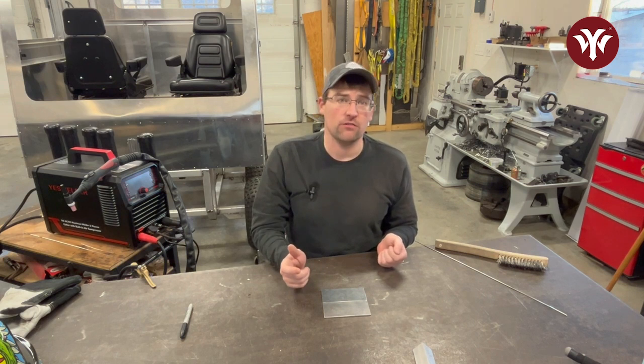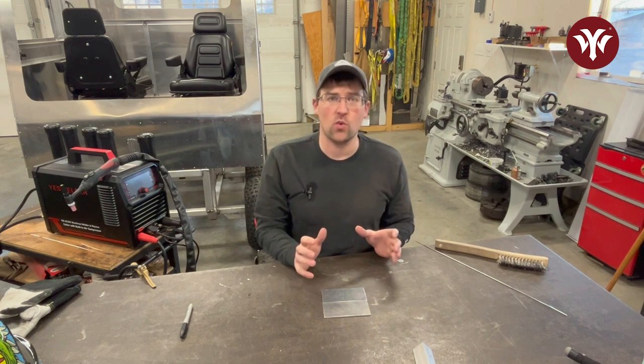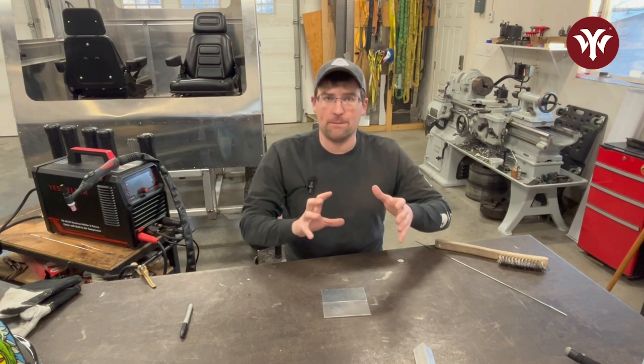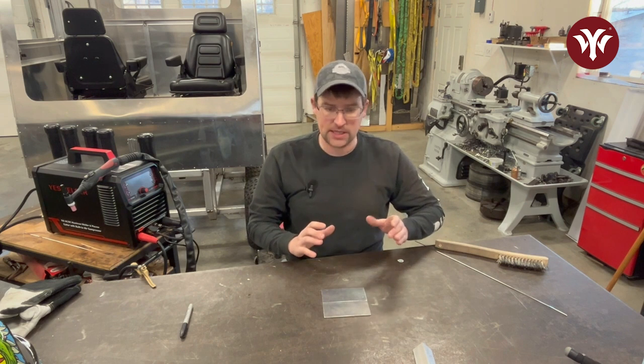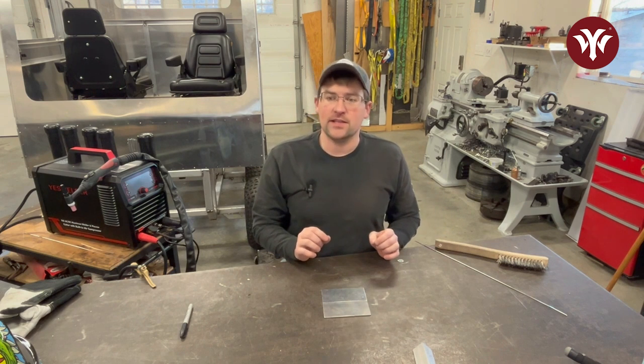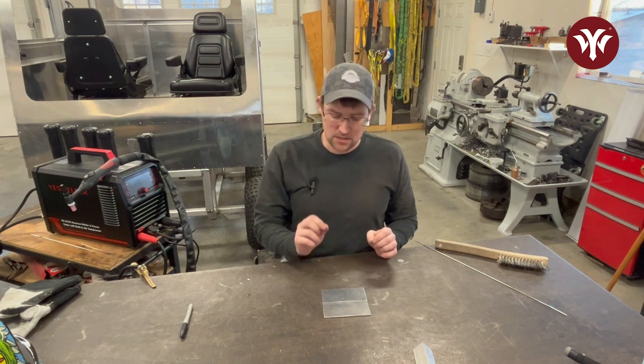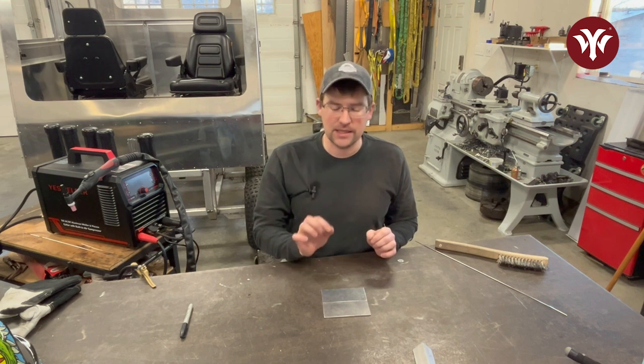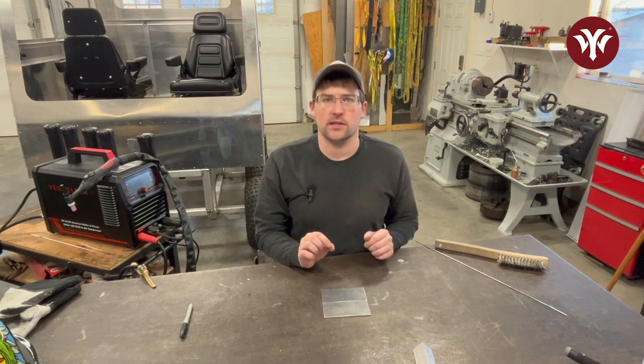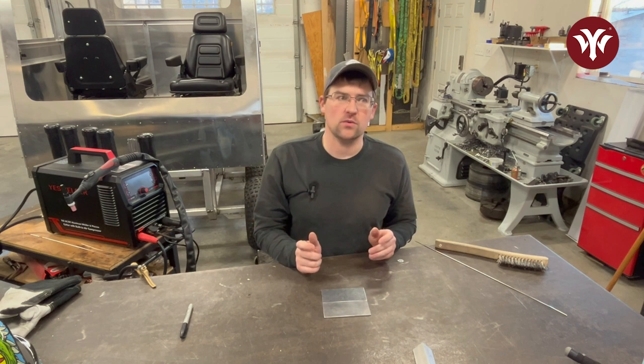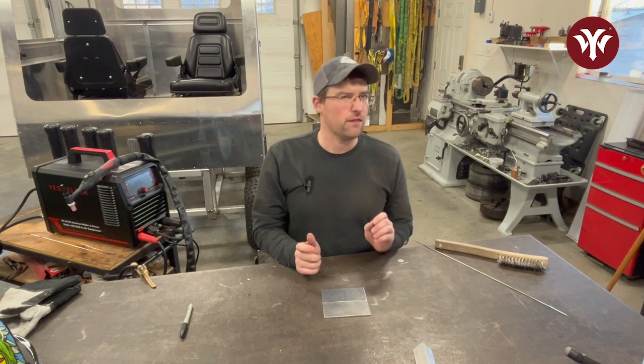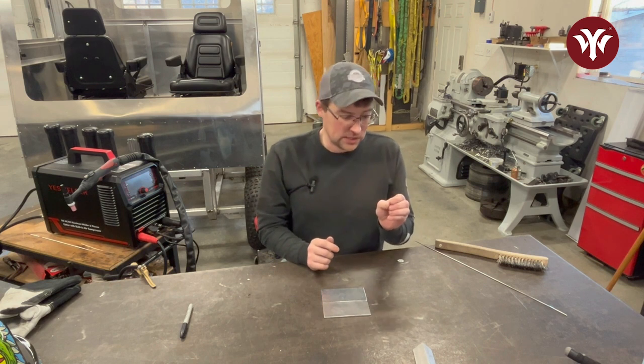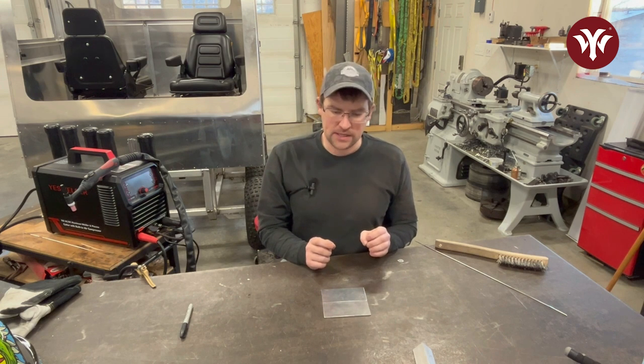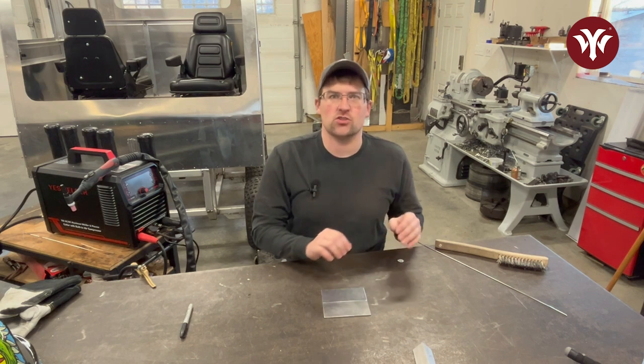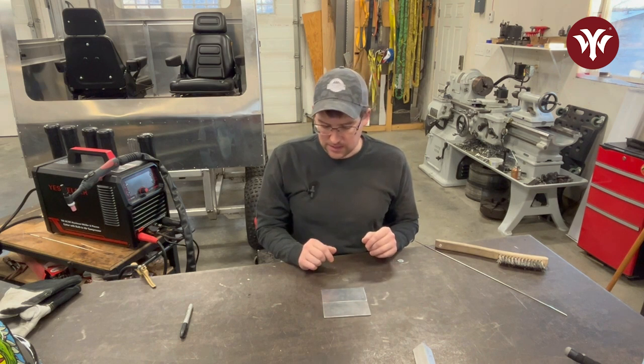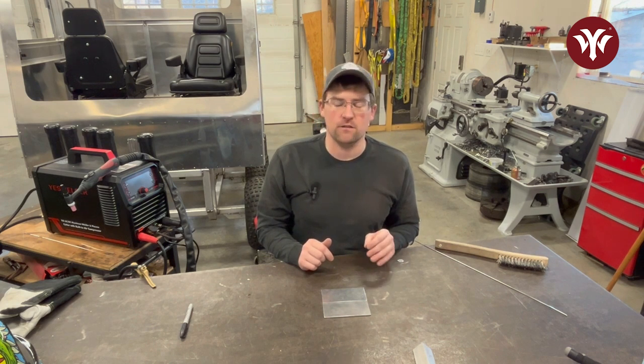And this can be critical. If you're welding on some components that you really don't want to overheat because it might warp the part or disfigure the shape or something like that, pulse welding lets you get the penetration and the weld completed with as little heat into the base material as possible. Usually it would be something you use when you're trying to weld thin metals and lay a bead on a really, really thin piece of aluminum, because you're not putting any extra heat in. It's not something I do a lot of.